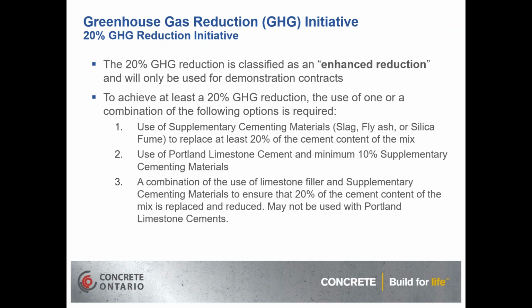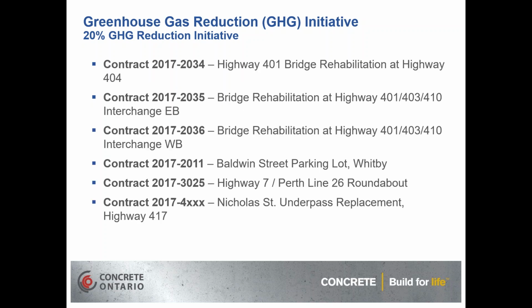Or we can use a combination of the limestone filler and the supplementary cementing materials to ensure that we get a 20% reduction to the cement content where the mix is being replaced, or where the cement is being replaced and reduced. And again, with the limestone fillers, they're not allowing using that with the Portland limestone cements.